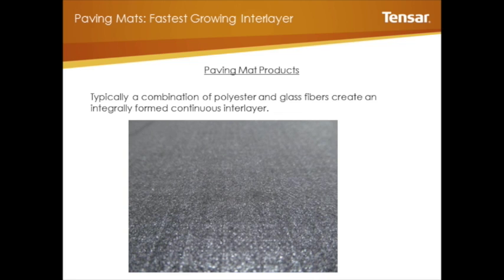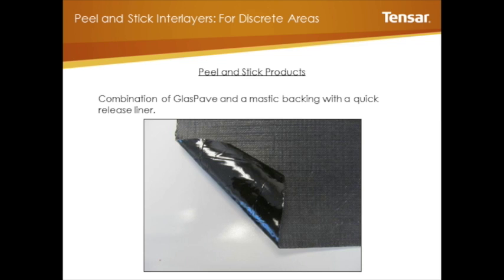So the paving mat really came about in that they were looking for a product that could give you the continuous moisture barrier benefits, but at the same time also perform more like a grid. So they came up with a material that can do both. Looks like a fabric and performs like a grid. And it's recyclable. So that was a great transition that has occurred, and you now have a paving mat available for your use. Another product that is also available is in conditions where you have distress in very localized areas.